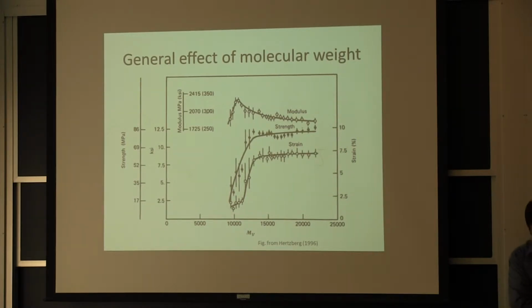This is something that happened a number of times. Yes? Anytime that you weld, you end up with a fusion line. So if I have one material here, and it's got all the microstructure, and I come with the other, it's got all the microstructure. The time that you have for mixing the two is very important in terms of when you're hot at high temperature and being able to take that long end of a macromolecule and getting into the other one, because that's what's going to give you long-term strength. If you don't get that, you have a big problem.